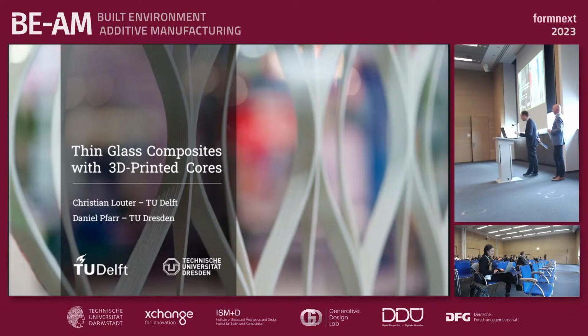So at first we looked into the A module of the building life cycle, so only the production of the materials and the CO2 emissions during production. The next one will be the living phase. So now we have to care about U values and performance in terms of thermal insulation and things like that. And we go the full circle until the D level, and we make concepts for how to recycle it. The UV hardening acrylic is very challenging to recycle because the bond is very strong and we can't really disassemble the whole product. The hot melt is a little bit more beneficial because we can just heat it up to 90 or 100 degrees and then we can take it off, so that's the idea. But yes, we're still working on concepts for how to completely disassemble the whole product, but that's still a way to go.